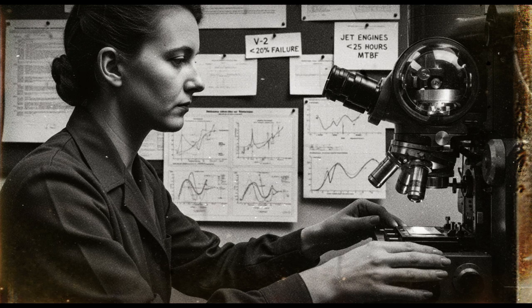Microscopic examination revealed that German forging operations were being conducted at temperatures too low for proper metal flow. Instead of creating strong, uniform grain structures, the forging process was creating areas of weakness where metal flow had been interrupted by improper temperature control.